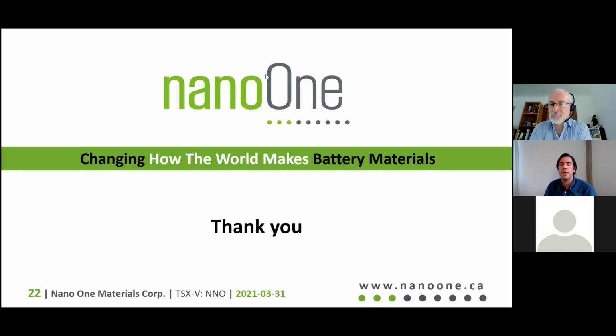I had a question about LMFP and how you rank that and how that stacks up in your estimation and your process towards that. There is an interest in lithium iron manganese phosphate. It's a mixed iron manganese phosphate because you get a higher voltage plateau, which is great. The reason why manganese is not used is because you need to put a carbon coating on the material to impart conductivity, because the phosphates themselves are not conductive at all. But the carbon doesn't stick to the manganese phosphate. It sticks to iron beautifully. It doesn't stick to manganese. So if you use just pure manganese phosphate, you can't carbon coat it.